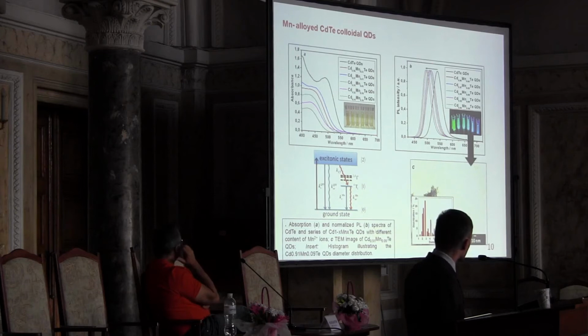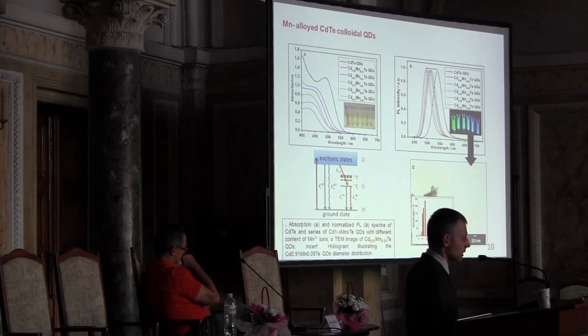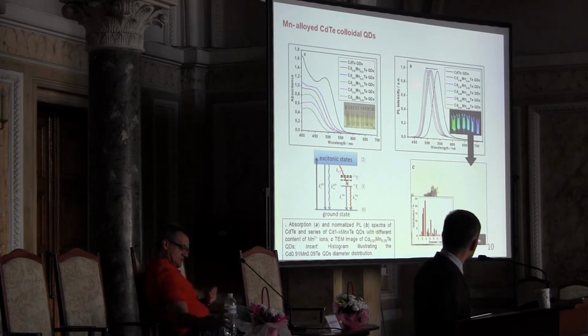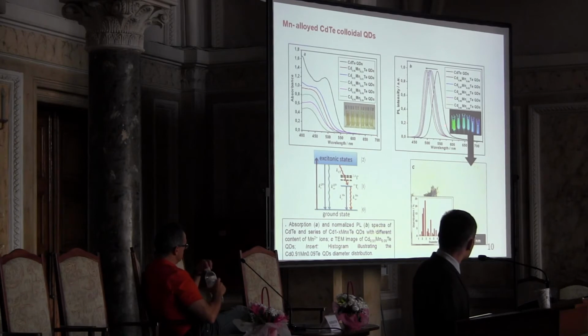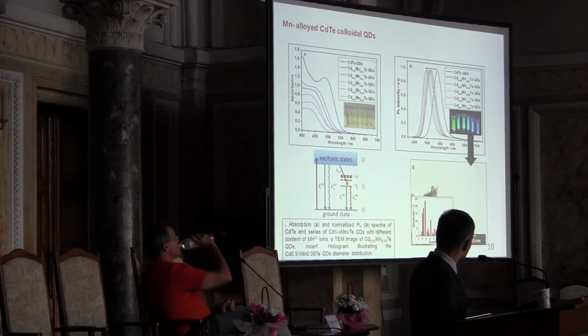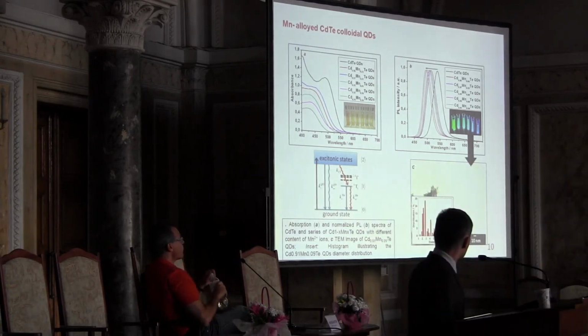Of course, there are some interesting magnetic properties expected and so on, but it's actually in water solutions. It's not a trivial task to dope cadmium telluride with manganese because of hydrolysis of manganese salts. It's quite difficult to do, but we somehow managed it. And what you can see here is that an increase of the manganese in the system shifts luminescence to the blue, which you can also see from the spectra.